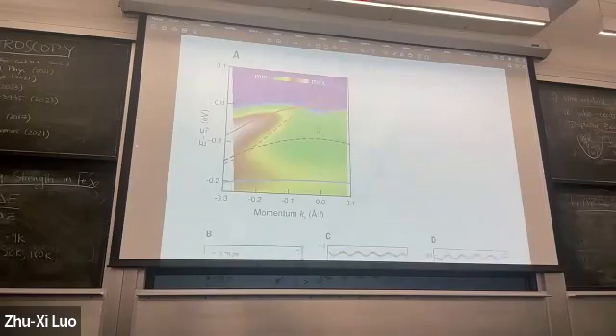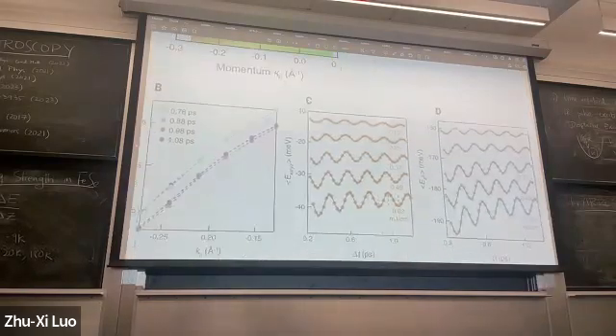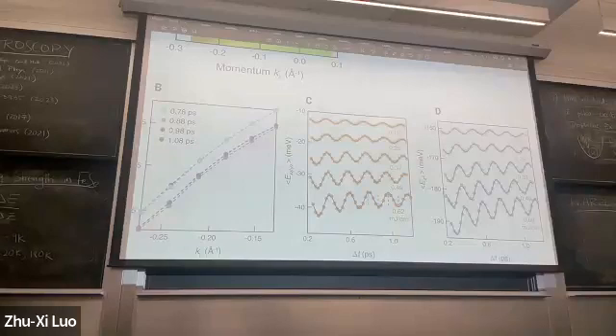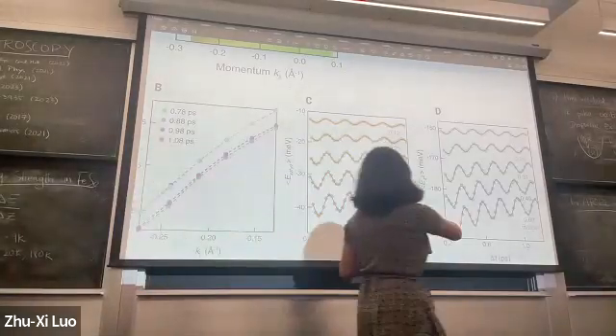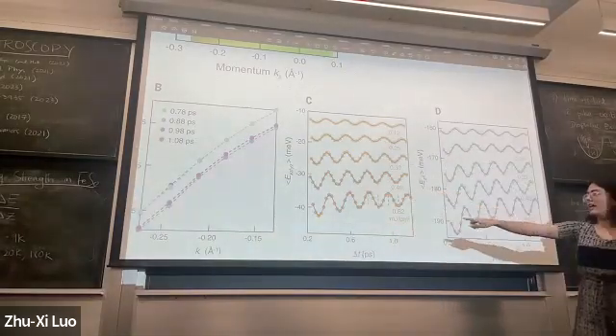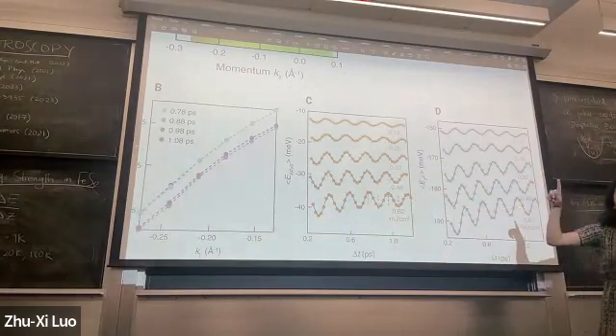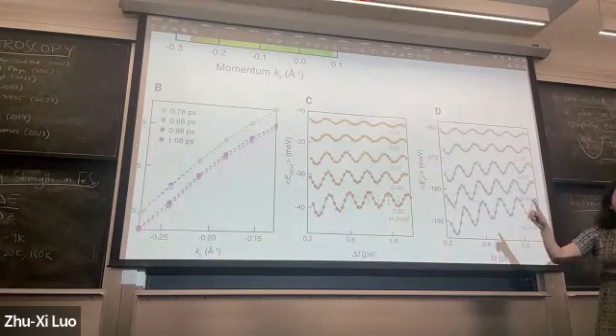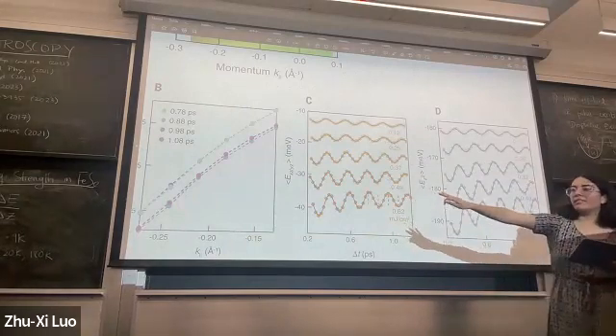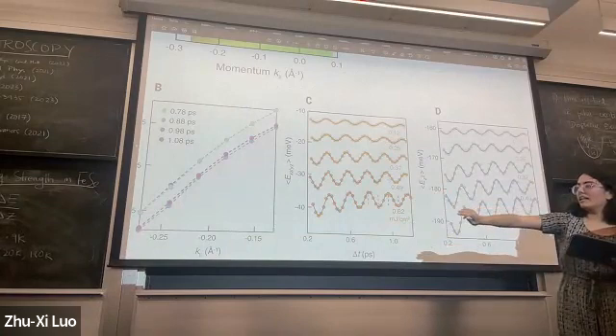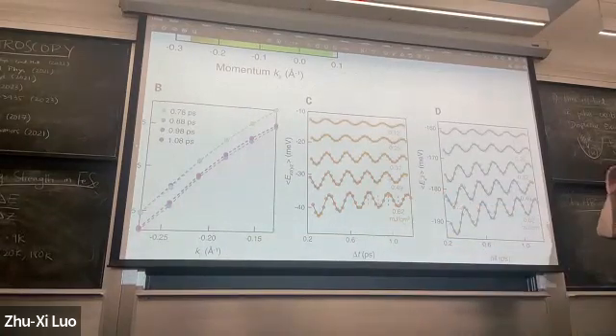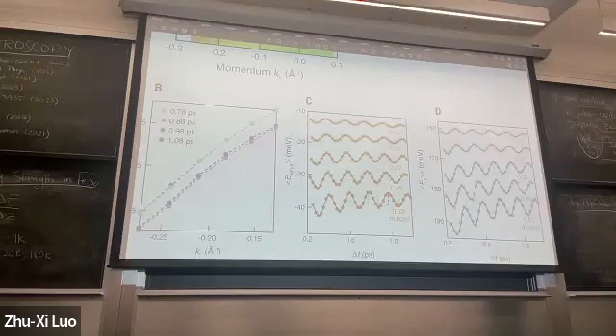Yeah, so this data down here, this delta T is the time delay. And this data again is for different laser intensities, looking at the oscillations of the peak of the energy of these bands as a function of time. And then the graph on the far right is looking at a fit to the band, the actual dispersion for various momenta, how that curve actually oscillates in time as well.